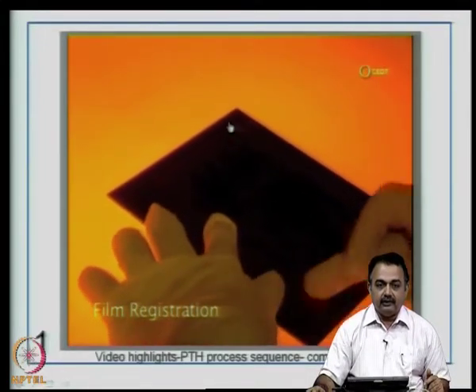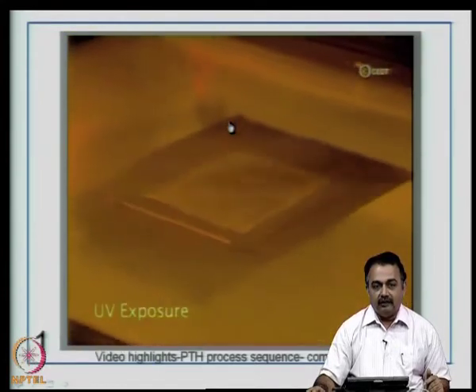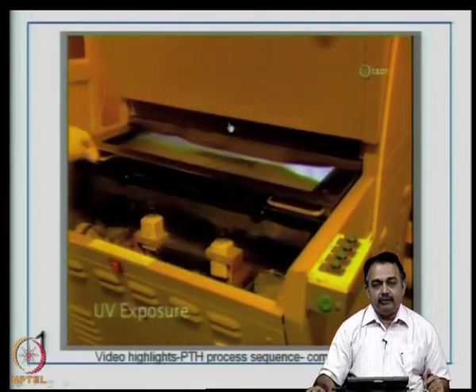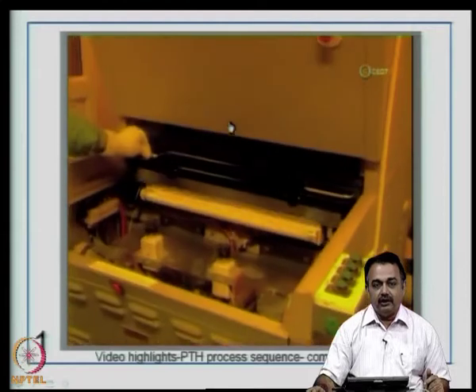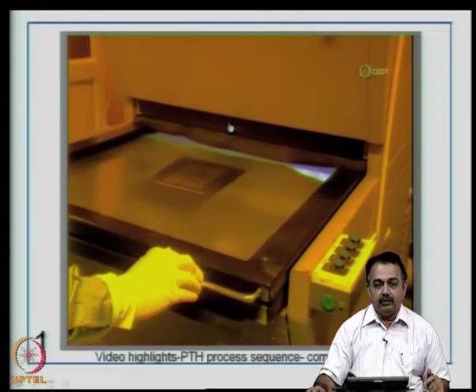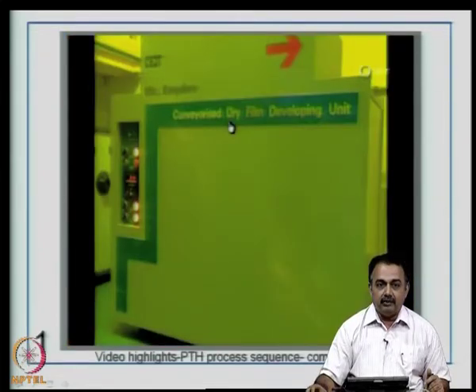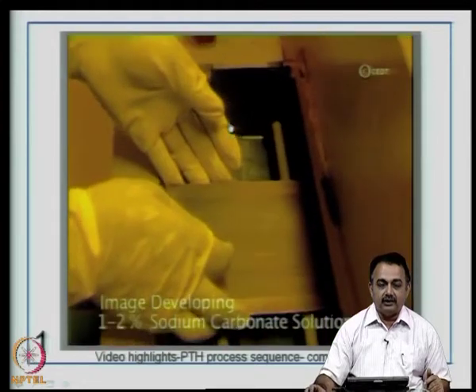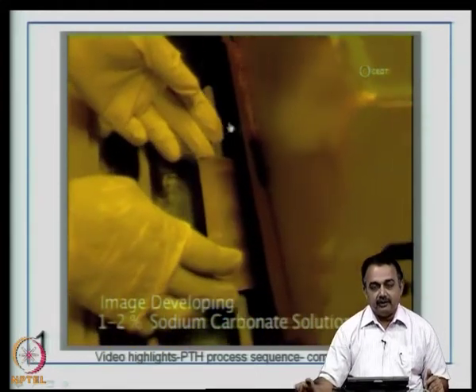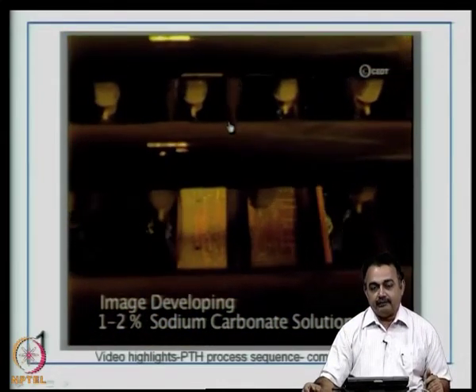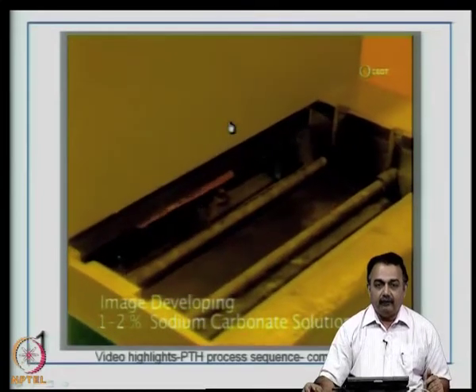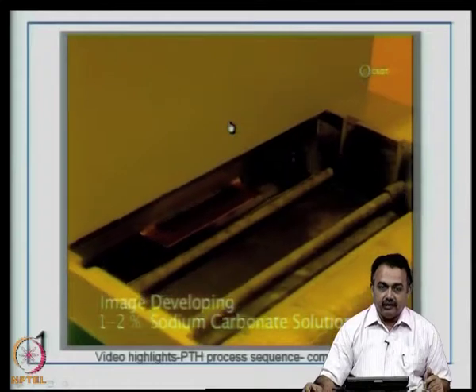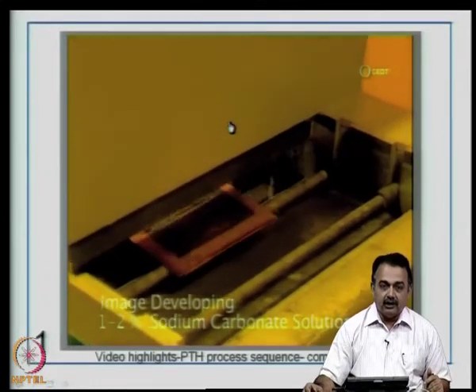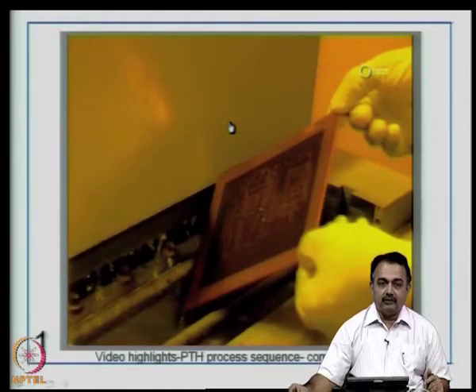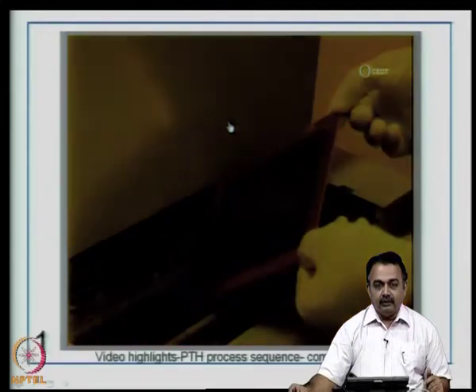The suitable masks for imaging the electrical layers are subsequently taken. They are aligned with the through holes that you have drilled, and then they are introduced into the UV exposure unit. You can see this is a UV exposure unit, where sufficient UV light is exposed to the dry film through the mask. Now, this will help establish an image. Now, this image is further stabilized by the developing process. So, the resist will be removed in the unwanted areas, and the resist will remain on the substrate where the circuit is to be protected, or in some cases where the circuit pattern requires additional copper to be added in terms of increasing the thickness of copper on the circuit areas. Now, this is the first step, that is the image transfer.